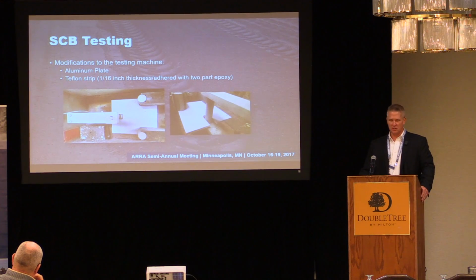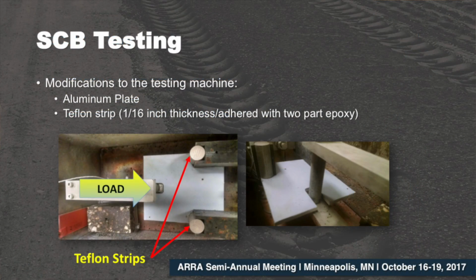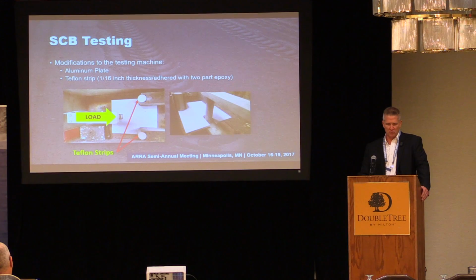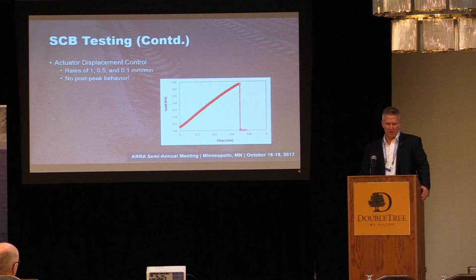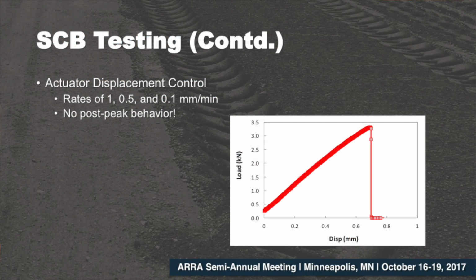So we did some modifications to the SCB test machine, mainly to reduce friction. Aluminum plate and Teflon strip were part of that. As you can see, the standard normal testing mode on SCB is compression as compared to DCT where it's tension. Beam fatigue is also compression. We tried to run the standard procedure that people were using for SCB, and what we found, looking at that load as it relates to the actuator displacement control, is we didn't get any beyond post-peak behavior.